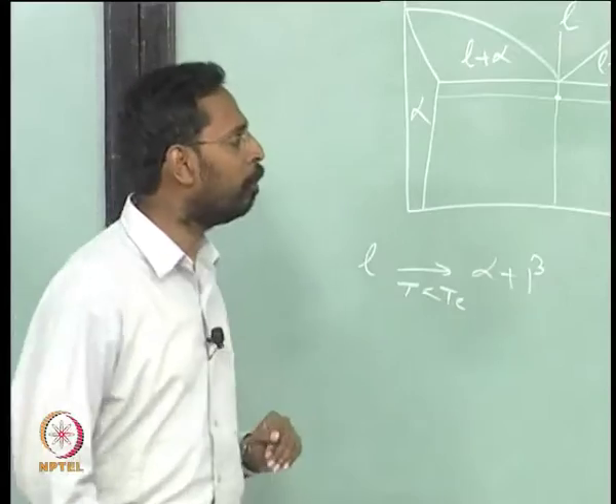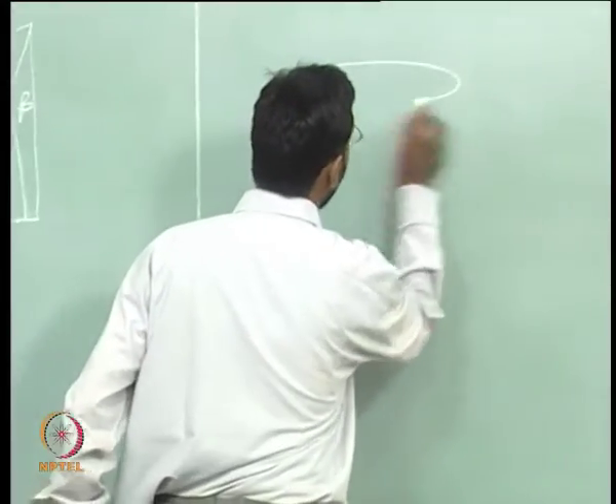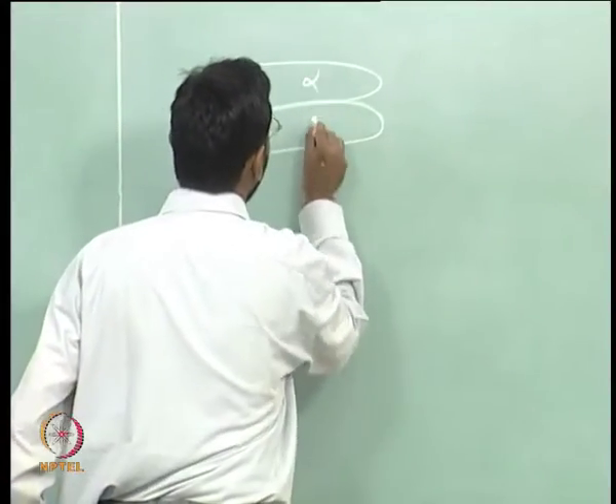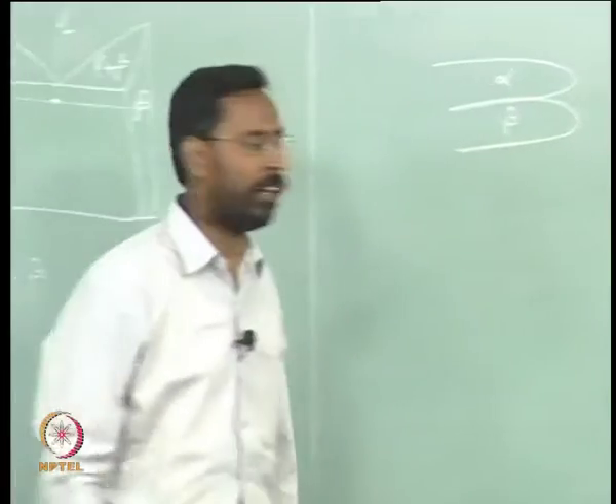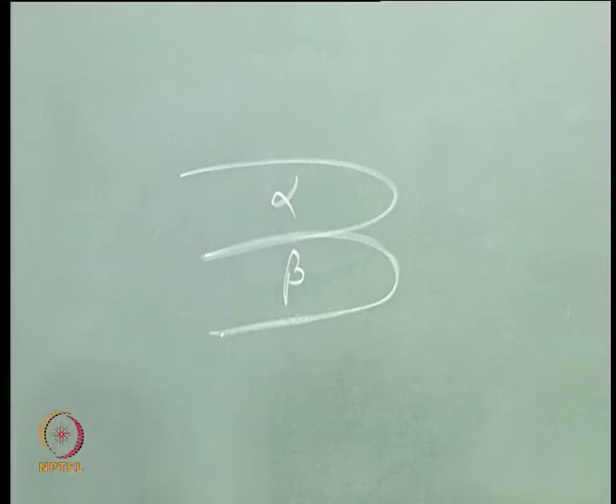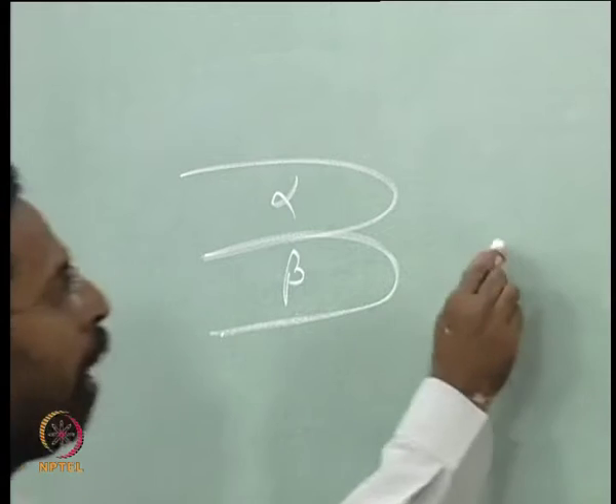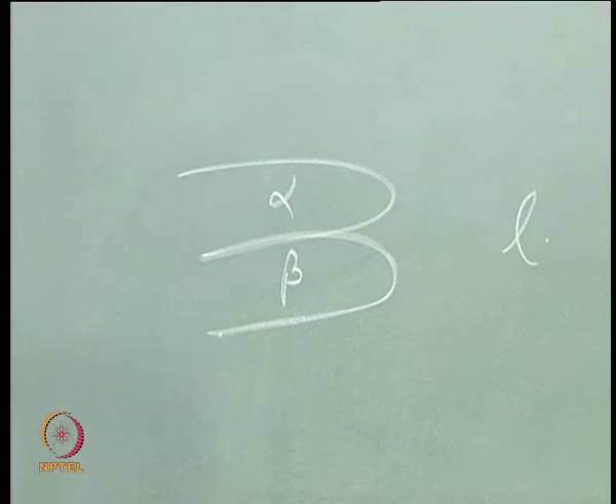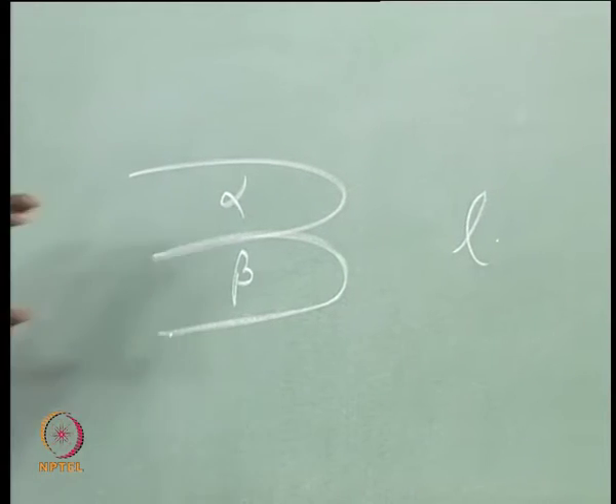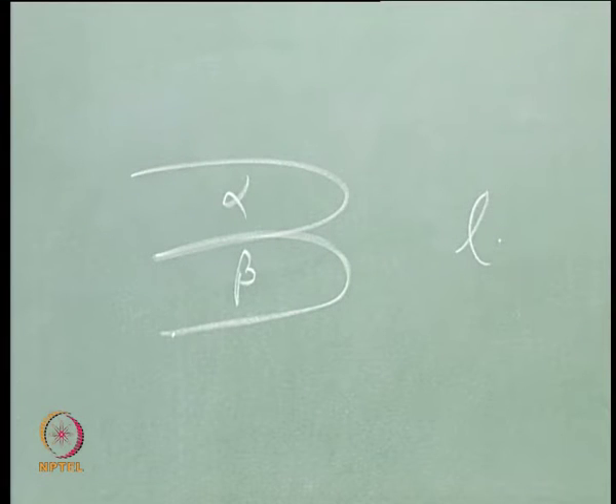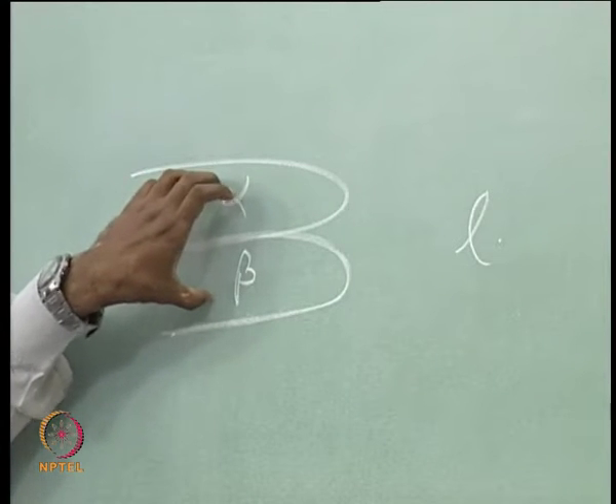But if you simply look at this alpha plus beta, which is nucleated inside a reservoir of liquid, so you have a liquid here, and this nucleus, a couple which has nucleated, alpha and beta always nucleate together if it is a lamellar eutectic. If it is not lamellar eutectic, they will not nucleate together, that also we will see it later. But assuming that they nucleate together, how do they grow?